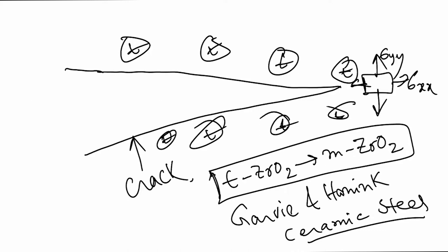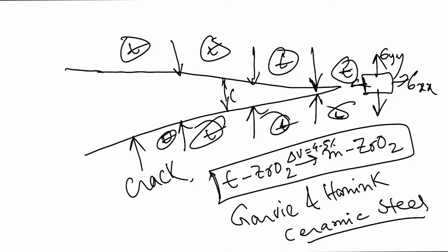Now, if tetragonal zirconia transforms to monoclinic zirconia, typically there is a volume expansion of 4 to 5%. So 4 to 5% volume expansion, what it does, it will induce compressive stress on the crack tip. And if these compressive stresses are realized at the crack tip, then what will happen? This crack opening displacement, that is called COD, crack opening displacement, is reduced, and therefore the crack tip will be blunted.